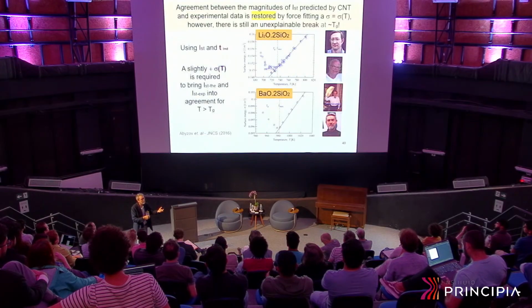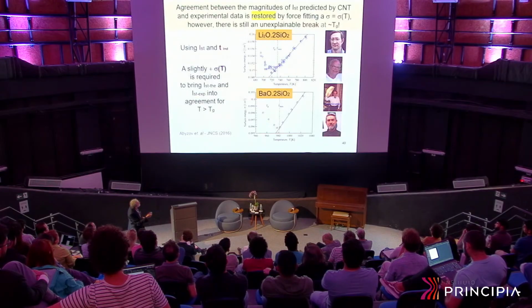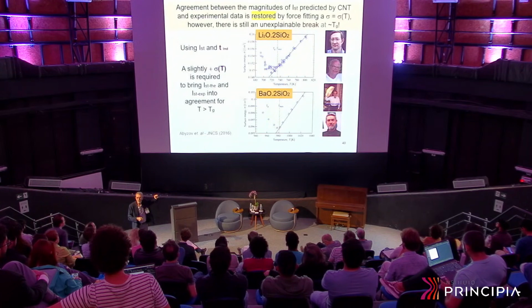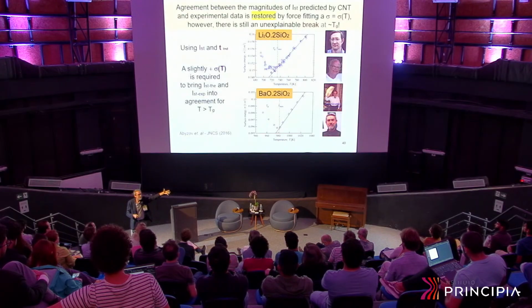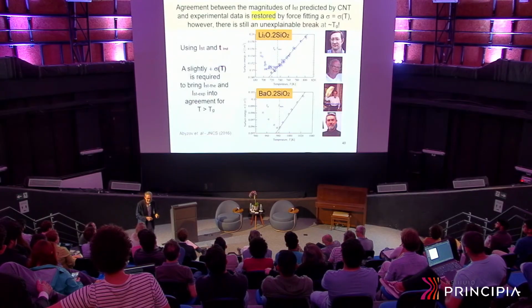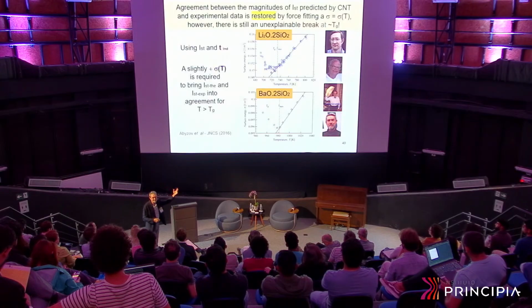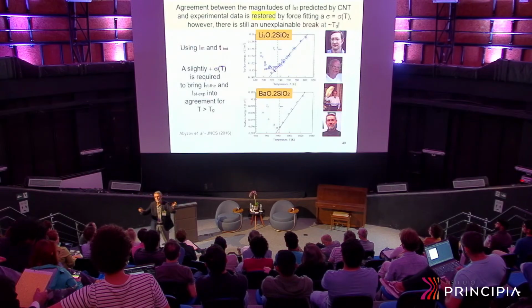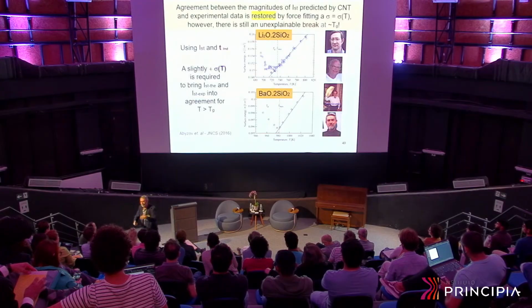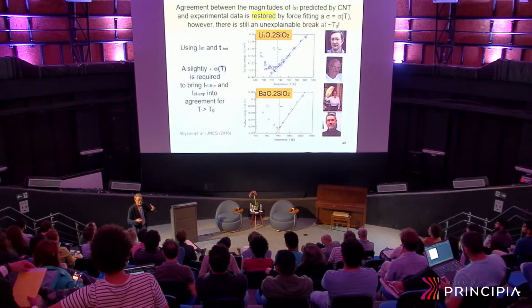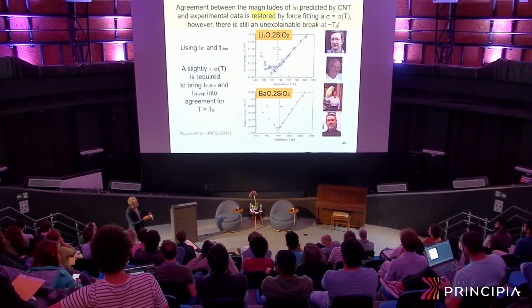It's an interfacial energy. And this little bit to the cubic power within the exponential. You remember, it's the exponent of interfacial energy to the cubic power. That brings back theory and experiments into accord. However, this is a force fitting. This, again, is not a test of the theory. Of course, you can publish papers with this. Any of these tests is a new paper, and that's how I made my career anyway, publishing papers on these tests. They say, oh, it doesn't work very well, but you can publish it.